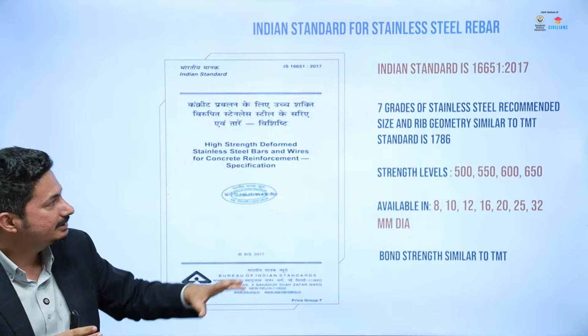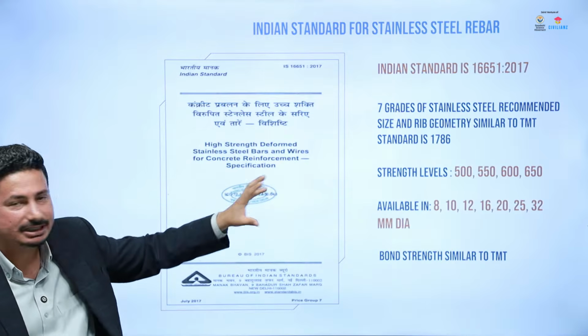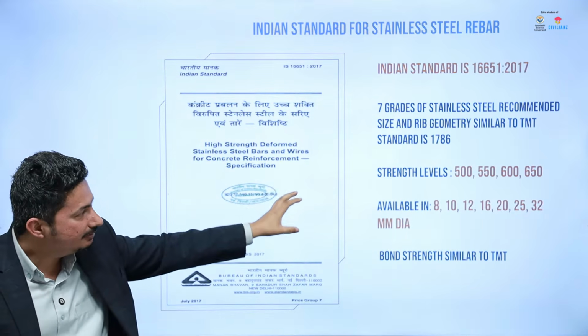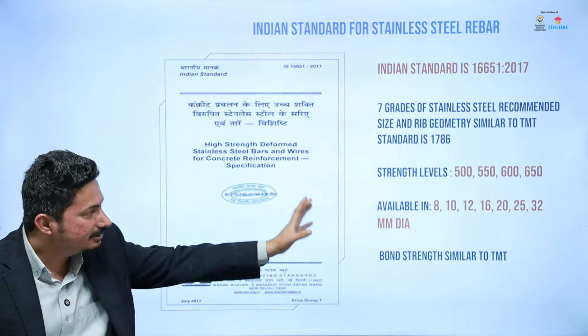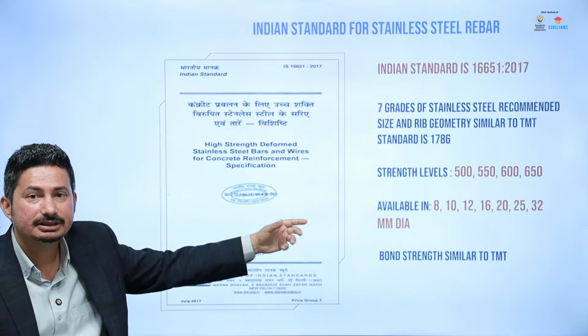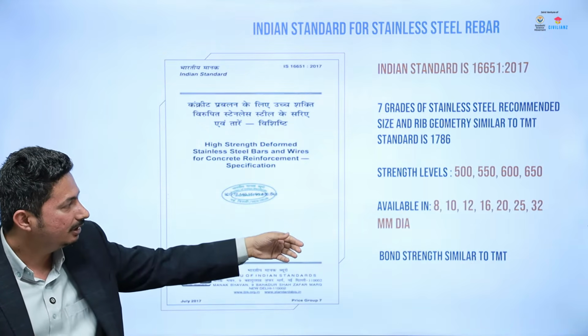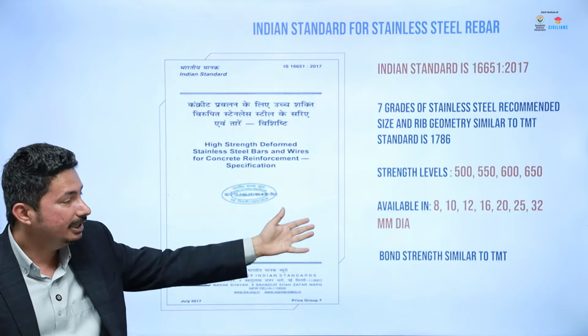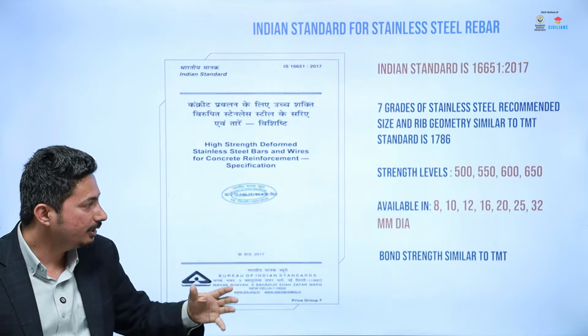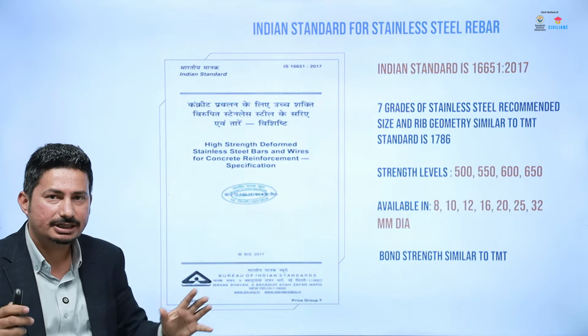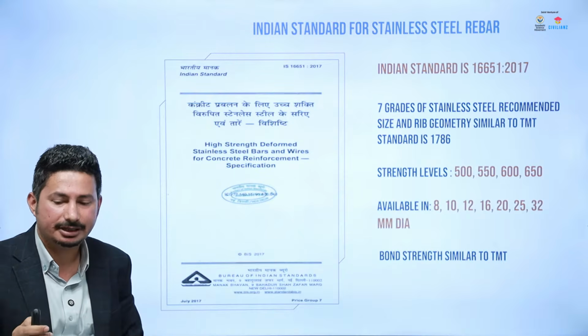Now, in this, there are 7 grades of stainless steel which have been recommended. The strength levels of 500, 550, 600, 650, which is at par with the TMT rebars, are provided. All the diameters from 8 mm till 32 mm have been provided. So, the BIS code is already in place where stainless steel rebar is incorporated.